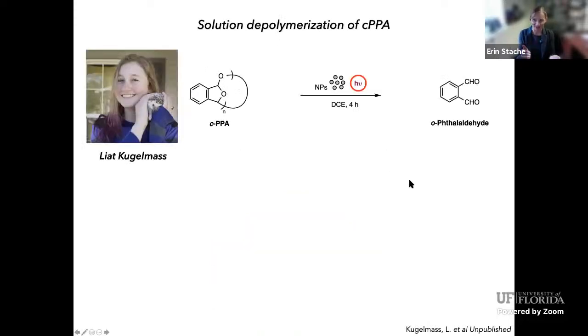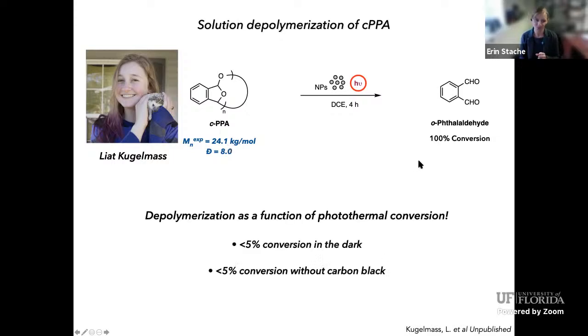And so all this work was carried out by Liat, who just introduced me before. She's a rising fourth-year graduate student in the lab, and she's responsible for everything that I'm going to be talking about today. What she did is she first synthesized some cyclic poly(phthalaldehyde), and then in the presence of carbon black in solution, which you can suspend through sonication, add in the polymer, expose it to red light, and after just 4 hours, we see 100% conversion to monomer. So she took this 24K polymer and converted it cleanly into monomer.